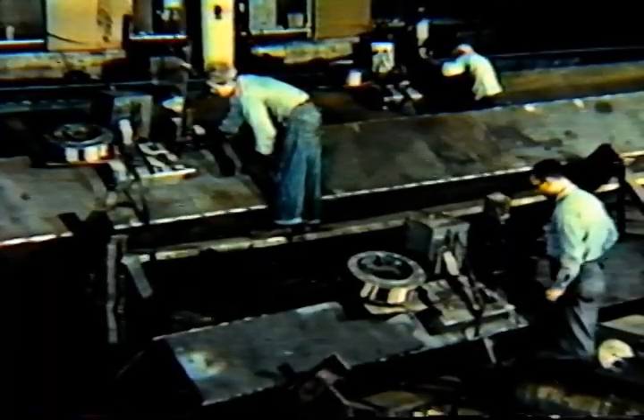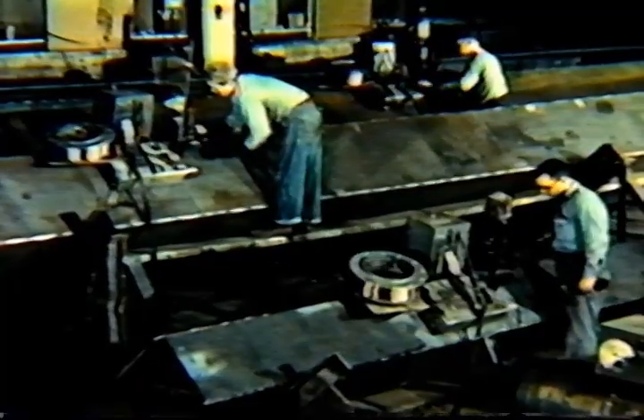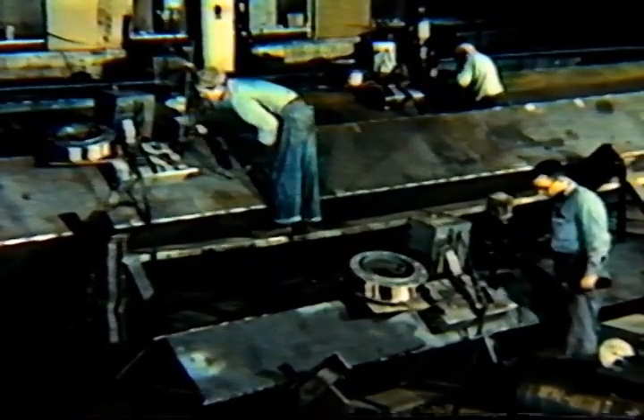These 3/8-inch fillet welds running the entire length of the sections were made at speeds in excess of 12 inches per minute with single electrode and 20 inches per minute with twin arc. On heavier sections, up to 38 passes were required to complete a single weld, as on this giant member, one of the 4 principal tower posts, the largest members in the bridge. Submerged arc welding produces smooth, uniform welds and minimizes warpage problems.